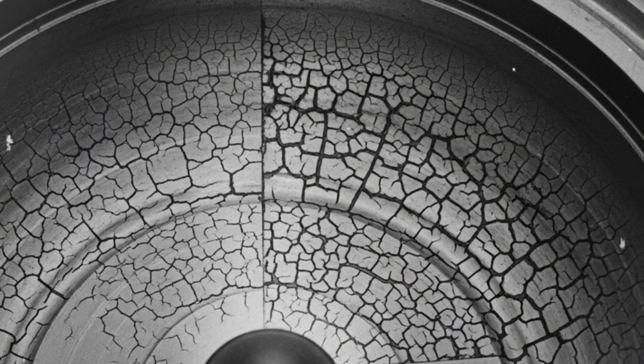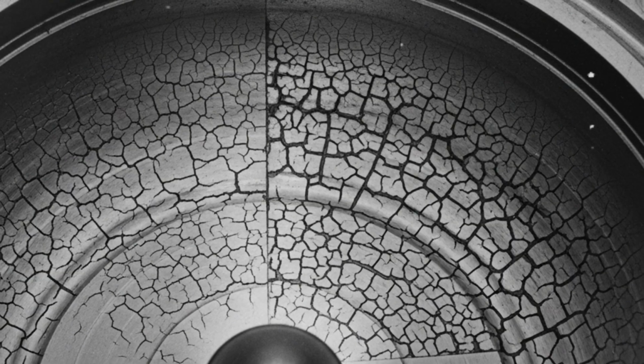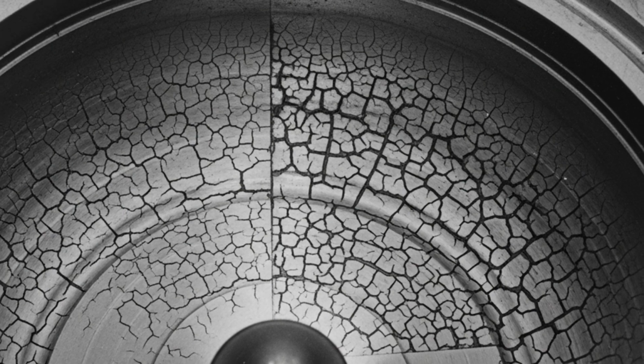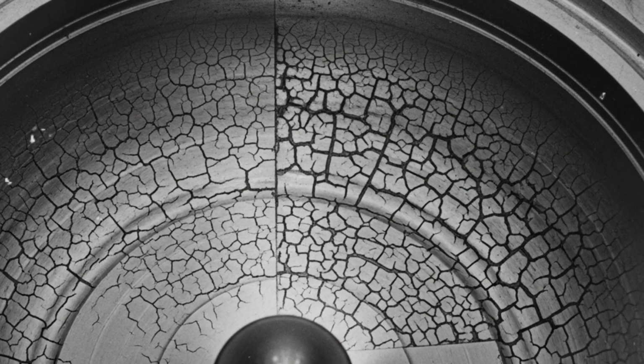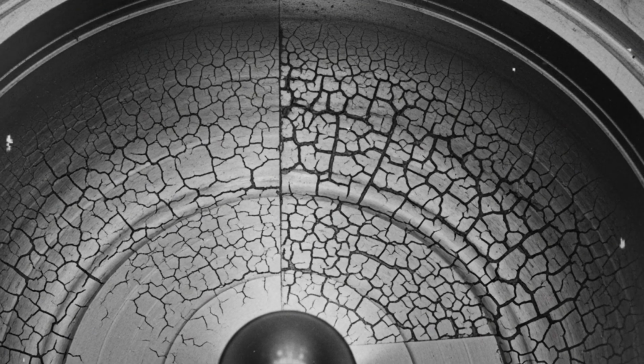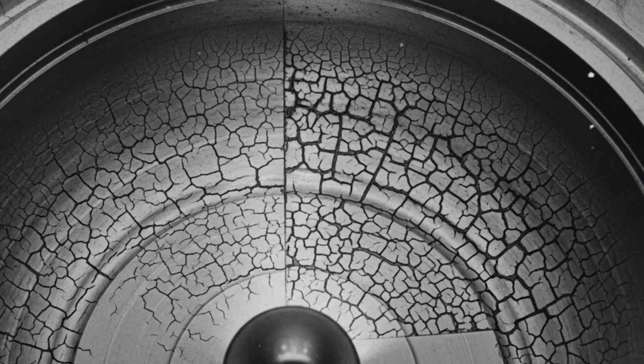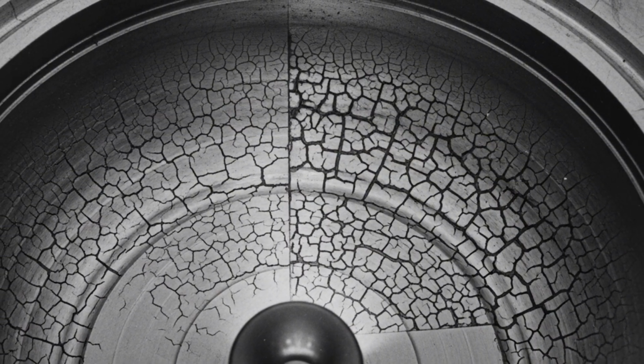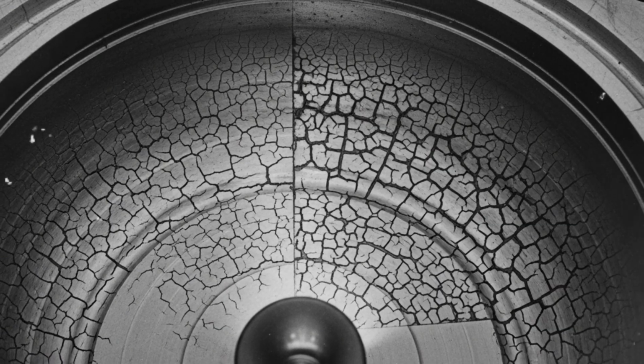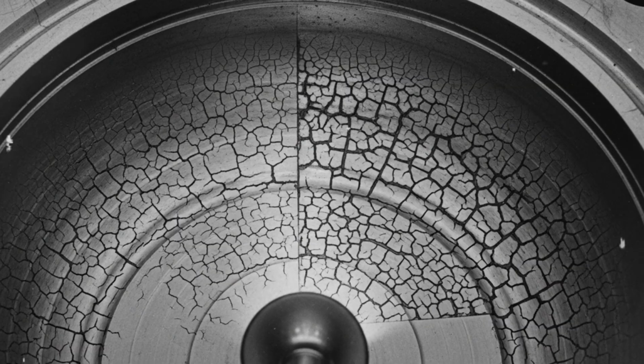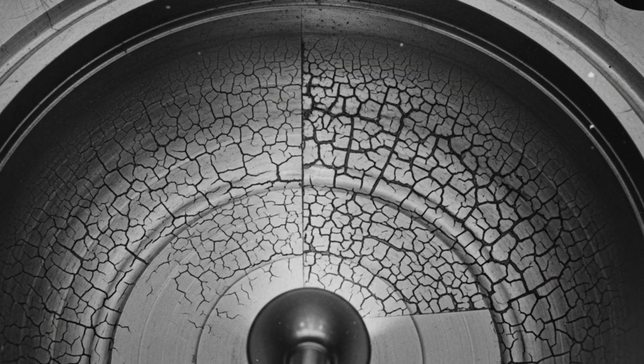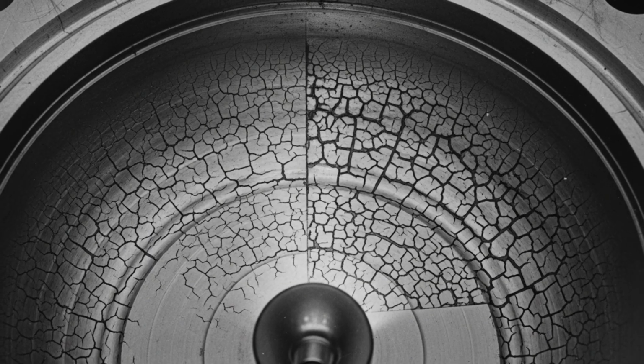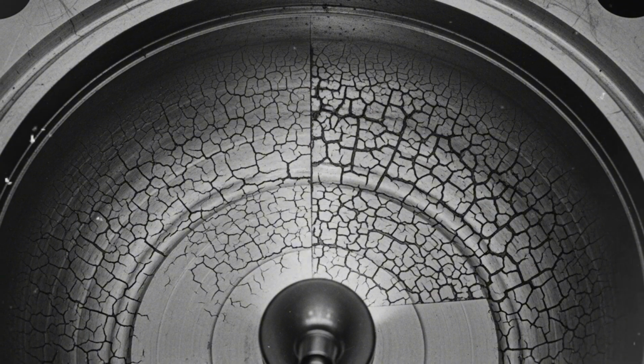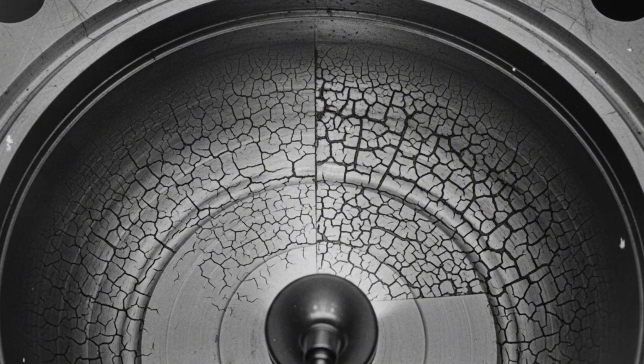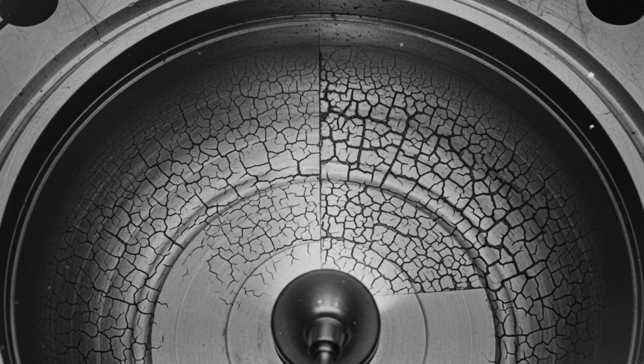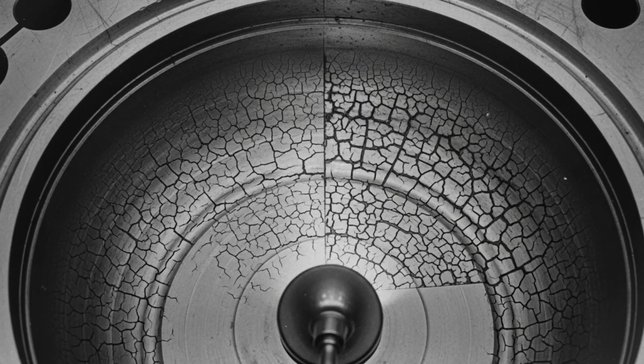The problem was that the transition between those two stages was not visually obvious. A die face exhibiting heat checking at a level that still fell within accepted production parameters looked, to an operator conducting a visual inspection between press cycles, very similar to a die face that had crossed the threshold into the range where a forging stroke could propagate one of those surface cracks through the die body and produce a catastrophic tool failure. The inspection techniques available to press floor personnel in the 1950s and 1960s, visual examination, occasionally supplemented by dye-penetrant testing when the foreman authorized the production delay that testing required, were inadequate to reliably distinguish between the two conditions.